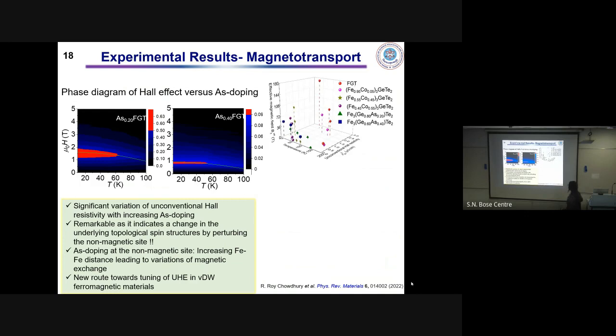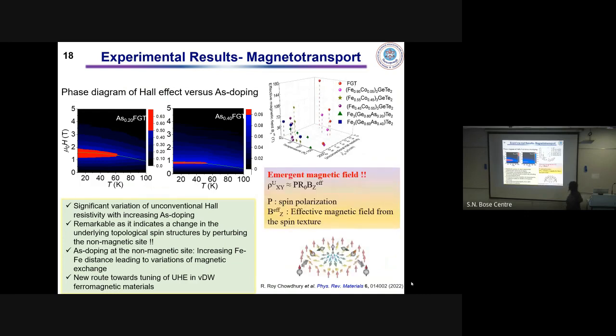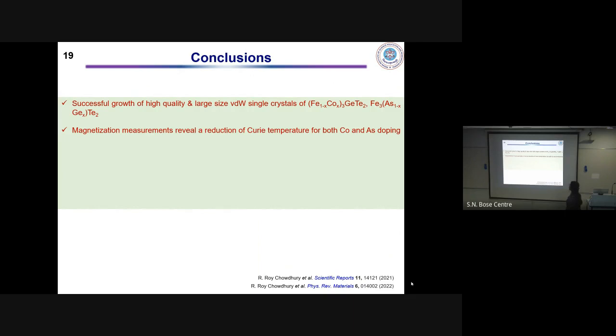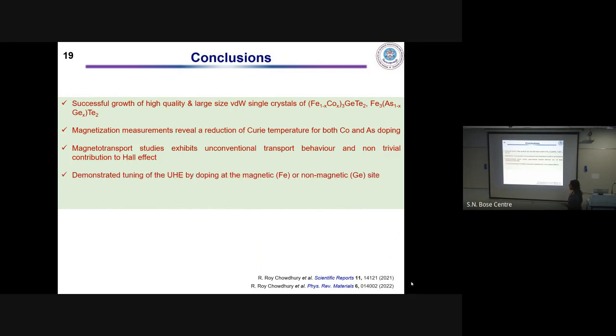Okay, so we have estimated the effective magnetic field, and what we can conclude from this part is that we have successfully grown high quality single crystals of Fe3GeTe2, which is a van der Waals ferromagnetic material, and we have doped it with cobalt at the magnetic site and arsenic at the non-magnetic site. The magnetization measurements reveal a reduction of the Curie temperature for both cobalt and arsenic. The magnetotransport studies exhibit unconventional transport behavior and a non-trivial contribution to the Hall effect, and we have demonstrated a tuning of the unconventional Hall effect by chemical doping.